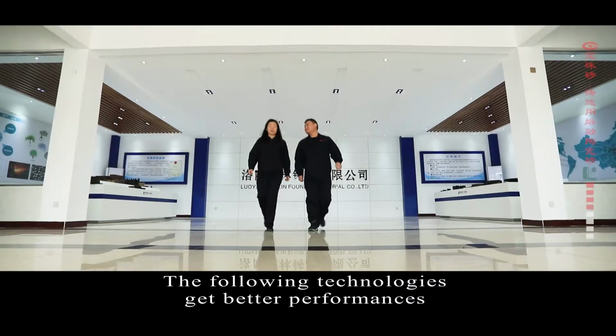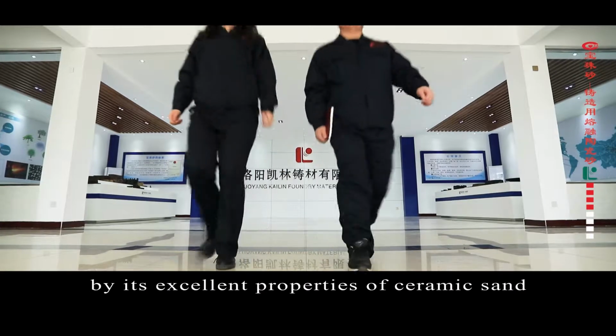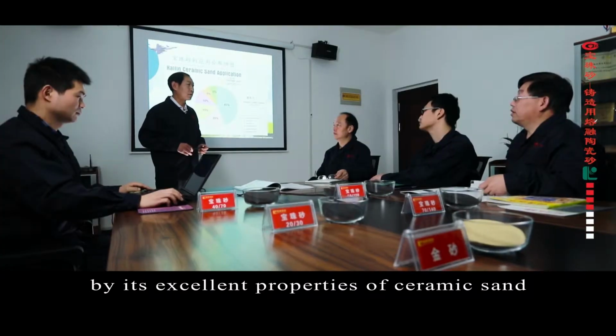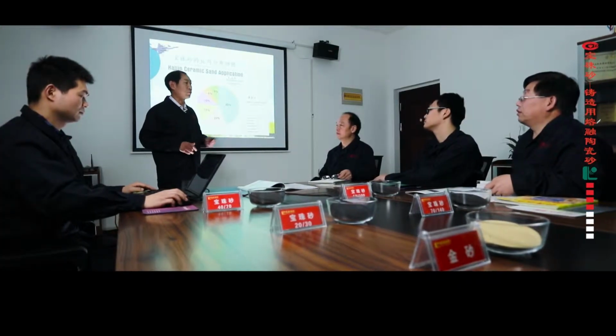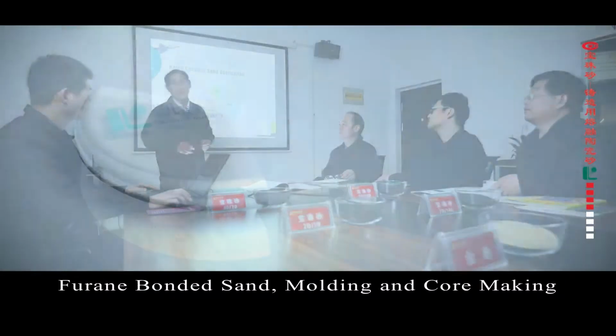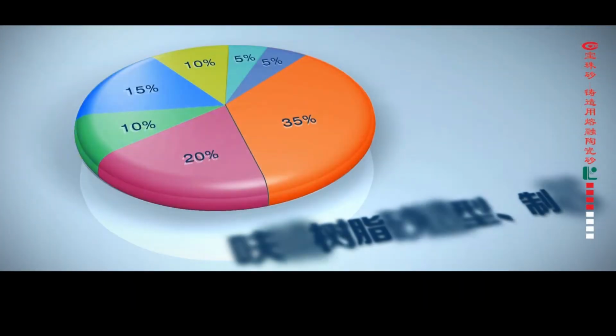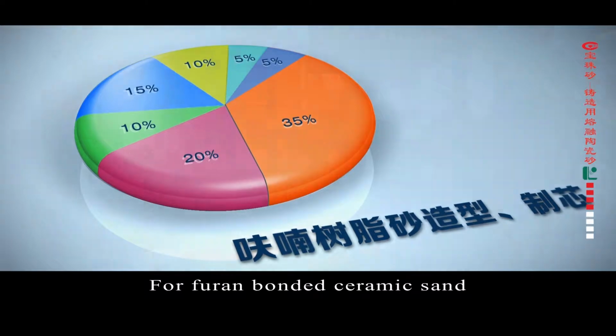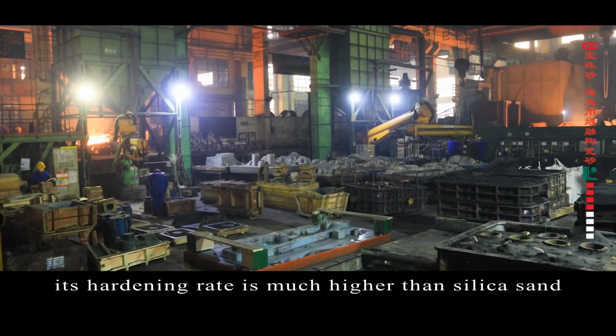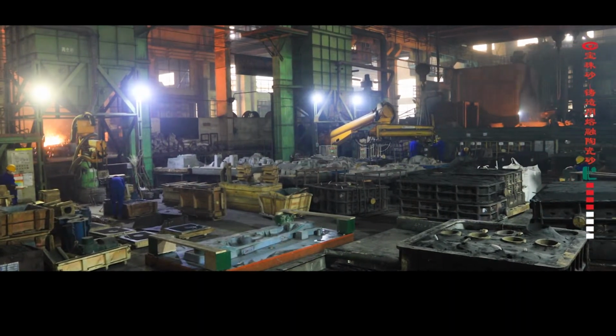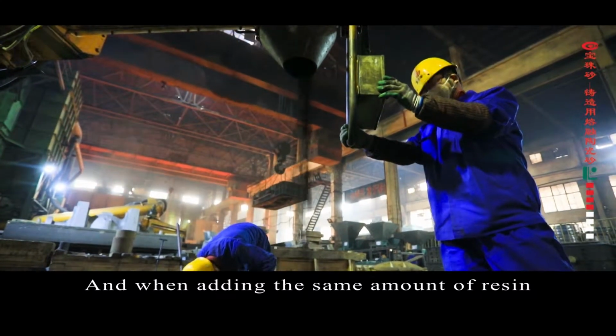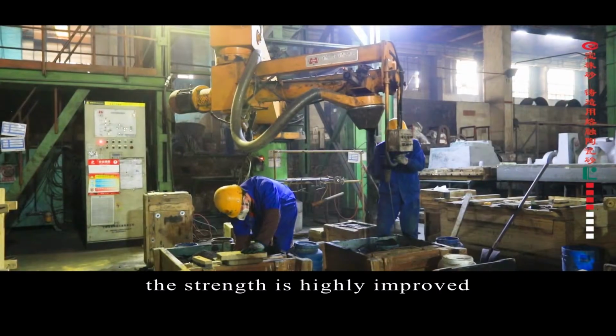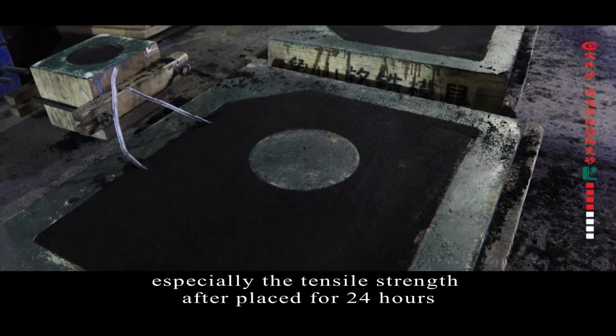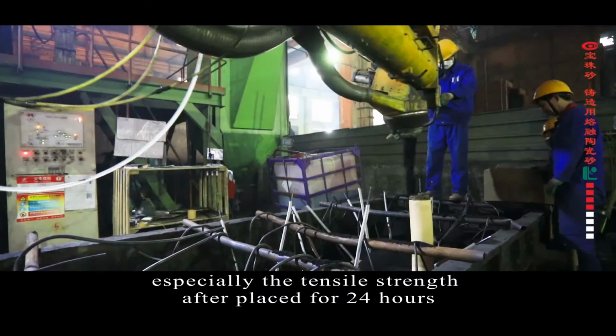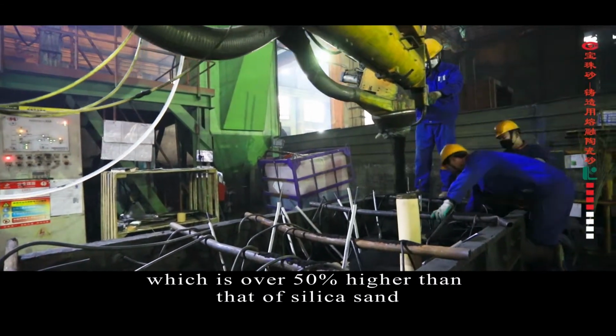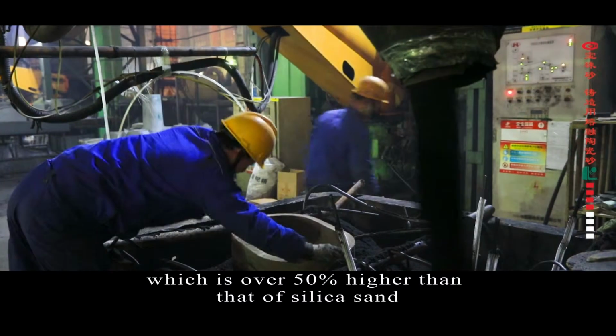The following technologies get better performances by the excellent properties of ceramic sand. 1. Furane bonded sand, molding and core making. For furane bonded ceramic sand, its hardening rate is much higher than silica sand. And when adding the same amount of resin, the strength is highly improved, especially the tensile strength after being placed for 24 hours, which is over 50% higher than that of silica sand.